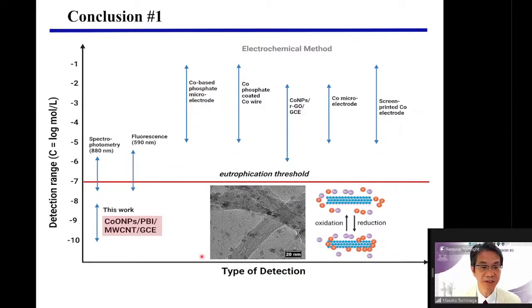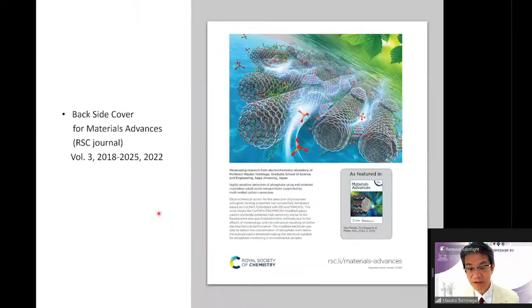Okay, as a conclusion, we developed a very high sensitivity phosphate ion sensor. Previously, electrochemical sensors to detect phosphate ion were not highly sensitive, but when I use a cobalt nanoparticle modified electrode, I achieved a very high sensitivity phosphate ion sensor. This achievement is already published in this journal, and it was selected as the back cover.